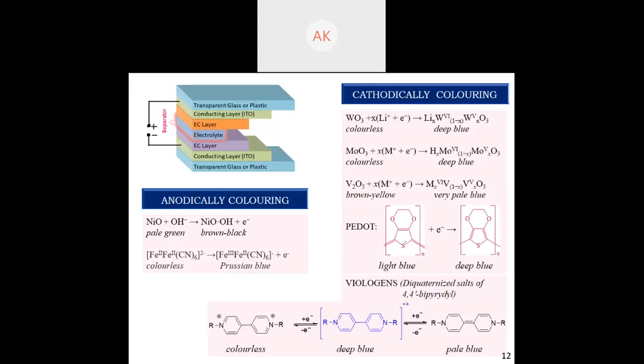Cathodically coloring materials are certain transition metal oxides like tungsten oxide, molybdenum oxide, vanadium pentoxide. Now, these metal oxides, upon concurrent intercalation of a metal cation and an electron, undergo reduction to form their respective bronzes. The lithium tungsten bronze, these are called bronzes. So what happens is, suppose in WO3, the W was in a +6 state, one of them gets reduced to the +5 state, which gives it the deep blue color.